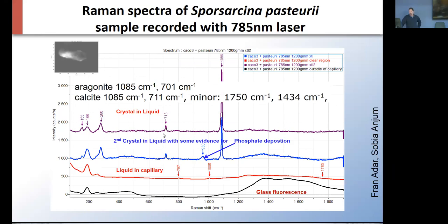Aragonite has a secondary peak at about 701 per centimeter, the wave number. Calcite has a secondary peak at 711. So this indicates to us that this is most likely calcite and not aragonite that has precipitated here. Again, non-destructively, and we can do it on the microscale.